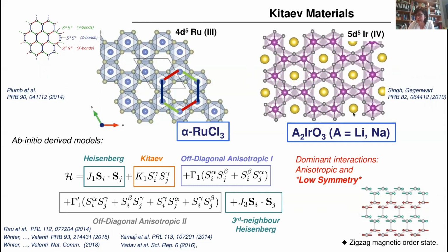This is now another class, the iridates. It's the same, also these planar layers of honeycomb lattice, but in this case separated by lithium layers. If you derive which are the important spin interactions in these systems, indeed the Kitaev interaction is the strongest one. That's why we call them Kitaev candidates.